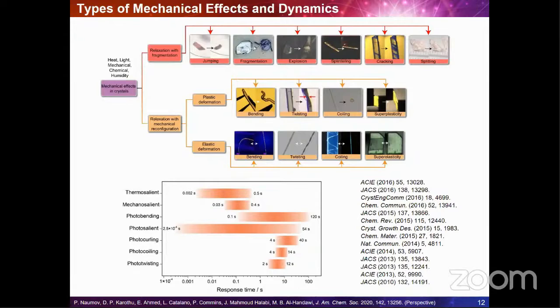So the classification has direct implications for the target applications and is also device specific. Depending on the deformation, we can have an application to different devices. For example, the restorative effects could be applied to devices which are based on cyclic operation, while disintegrative effects are more appropriate for single event operations. Whether a disintegration will occur depends on multiple factors, obviously, which include the susceptibility of the structure to stress and the rate of accumulation of various defects during the process. In general, the retention of integrity depends on the interplay between the time for the accumulation of elastic stress and the time for its dissipation. And I would say it also depends on the non-covalent interactions, which is why I'm presenting this at this meeting.